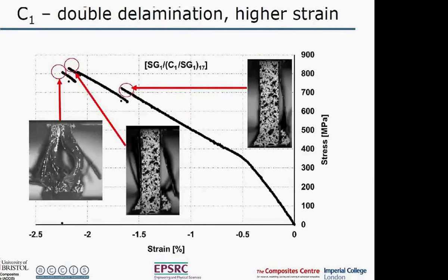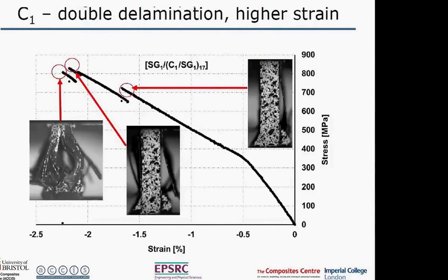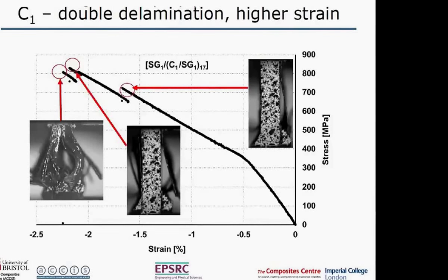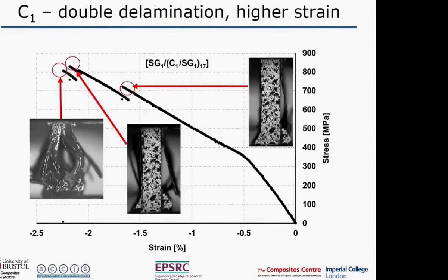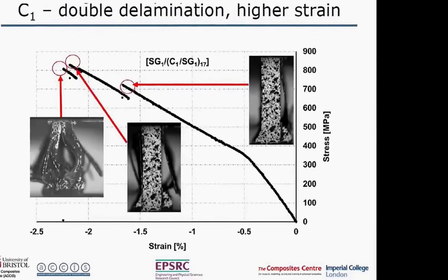And the strains here are quite a bit higher than they were with the ones with the thicker carbon. So we're seeing the same trends qualitatively as we saw in tension, that the thickness of that carbon ply is important in controlling when and if you get delamination.